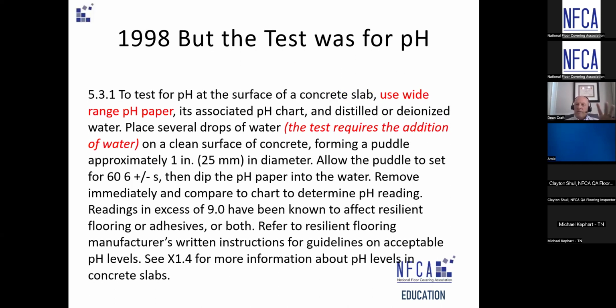This was the test. This was the pH test. It was embedded in the standard as far back as 1998, and it was the pH paper. Drop of water, wait 60 seconds, test it with pH. And if you're familiar with the calcium chloride test, many, if not all, of the manufacturers of the calcium chloride test also include pH paper in that kit. That's not a coincidence, because in 1998, those were the two tests required.